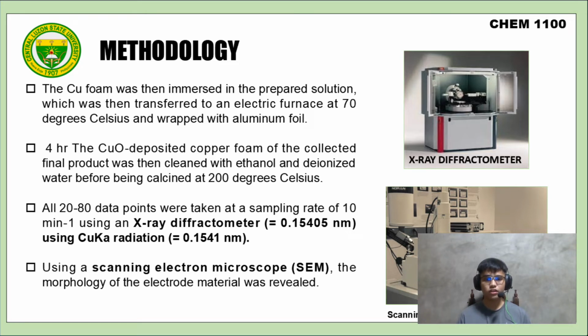One, using an X-ray diffractometer, with wavelength equal to 0.15405 nanometer, and using copper K alpha radiation, which is equal to 0.1541 nanometer. X-ray diffractometer or XRD allows one to ascertain the molecular structure of a crystalline material by diffracting X-rays through the sample. The X-ray diffractometer analyzer obtains interference patterns reflecting lattice structures by varying the angle of incidence of the X-ray beam.